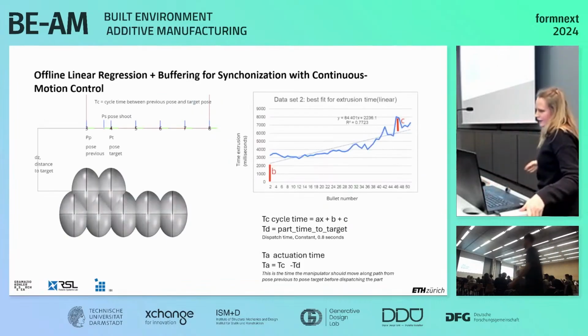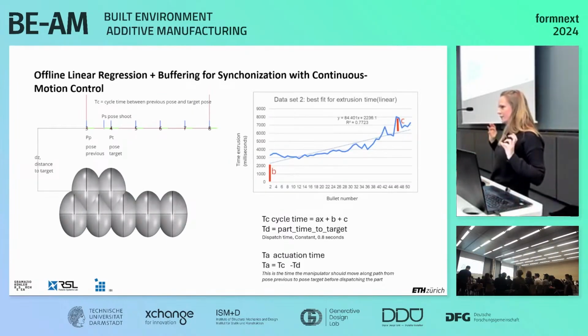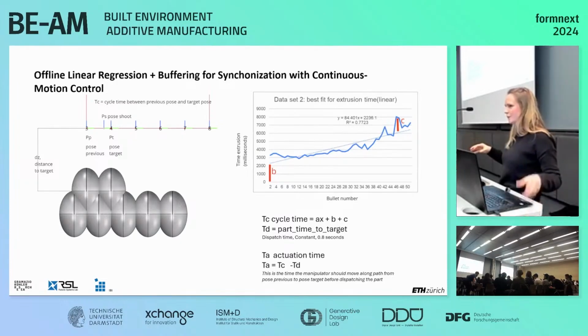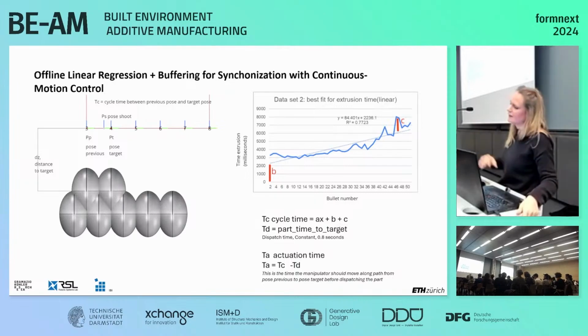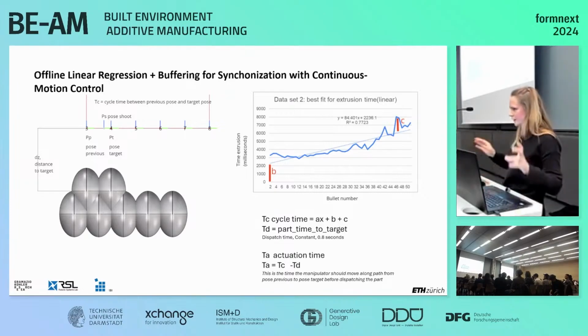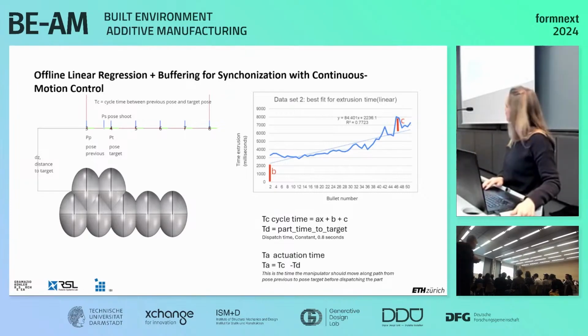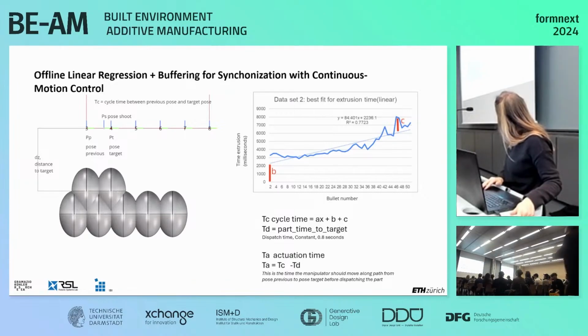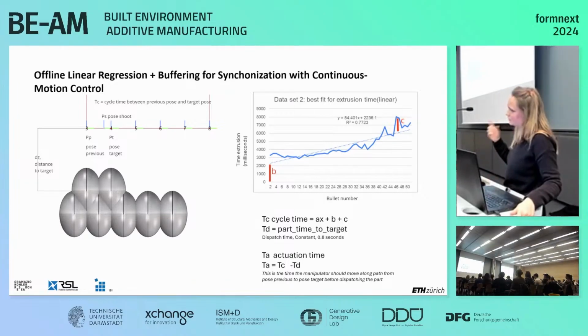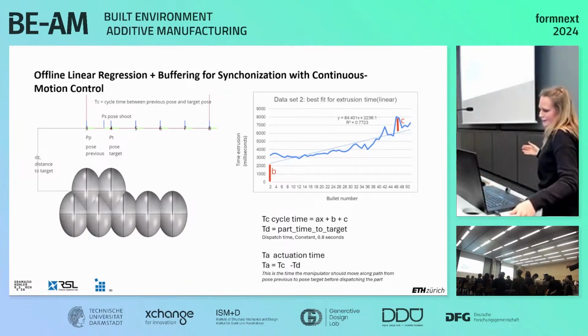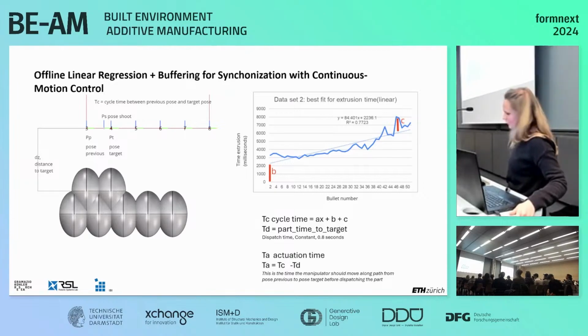So one of the big challenges is that we're not approaching extrusion-based 3D printing with a tight synchronization between the material delivery and the robotic system. Actually, when you extrude through a hopper-based strategy, you get an increase in extrusion time. So we developed something to synchronize these two systems, which is based on offline linear regression. So as you extrude, if you run at a constant velocity, it'll take longer to extrude. So basically, we predict how long it will extrude with linear regression.